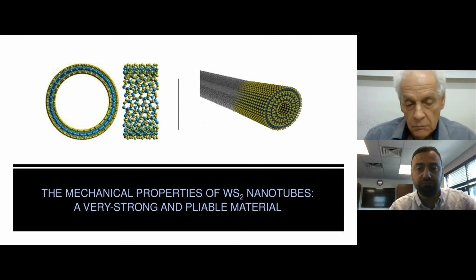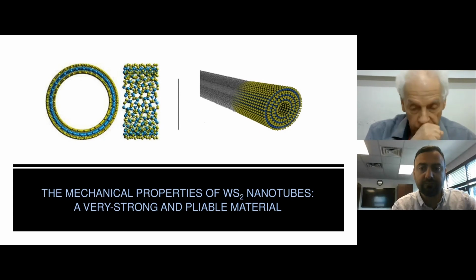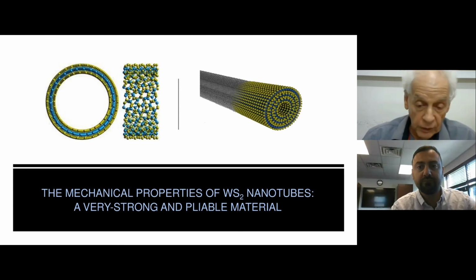I guess we use two or three different procedures. We use casting, namely we prepare a solution and dissolve or disperse the nanoparticles or nanotubes in polymer and solvent, then slowly evaporate the solvent, and a film forms. This is one way. The other way is, as I mentioned, through 3D printing.